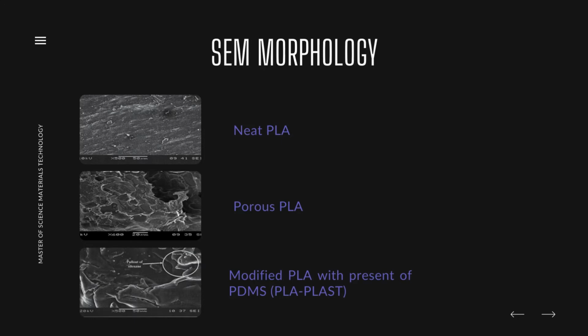For the PLA plus or modified PLA with presence of PDMS, it clearly shows that the surface of porous PLA were impregnated with pure PDMS. These have enhanced the surface to improve its mechanical properties. It can also be shown the siloxane crosslink samples exhibit smoother fracture and surface show pull out of siloxane.